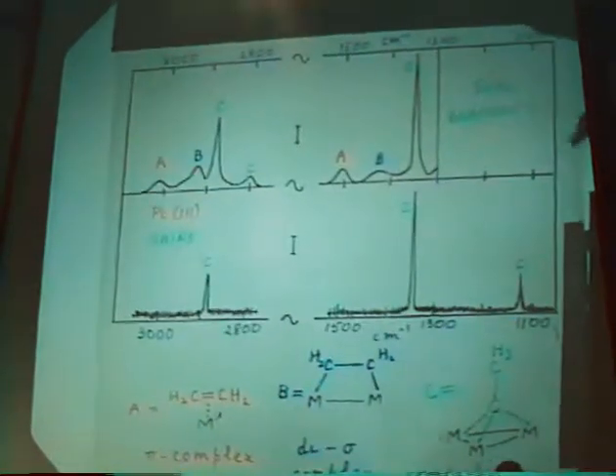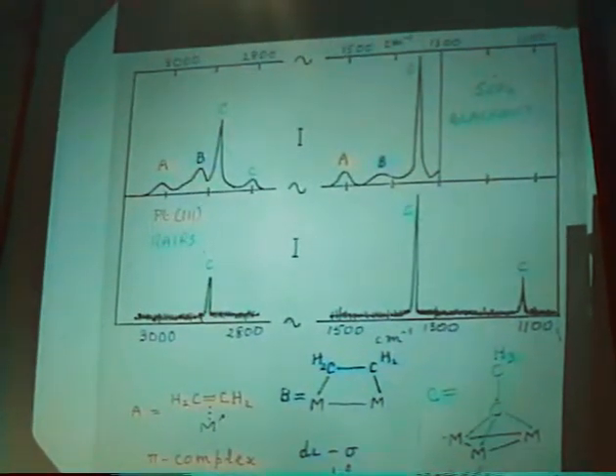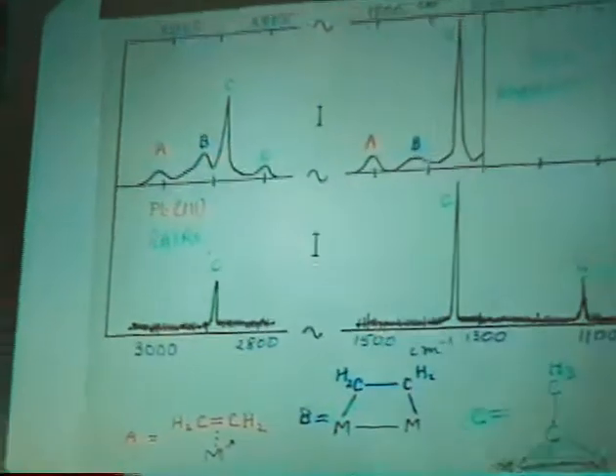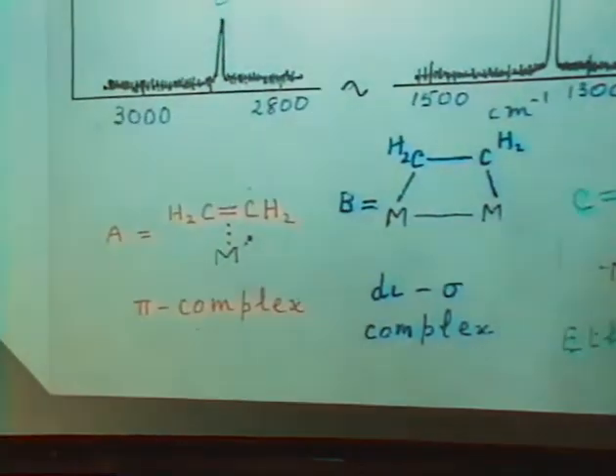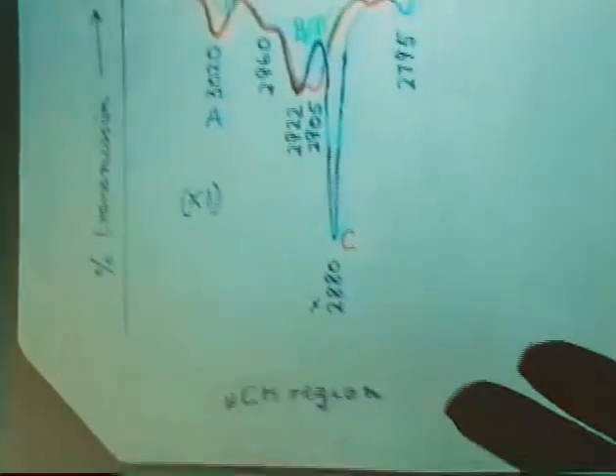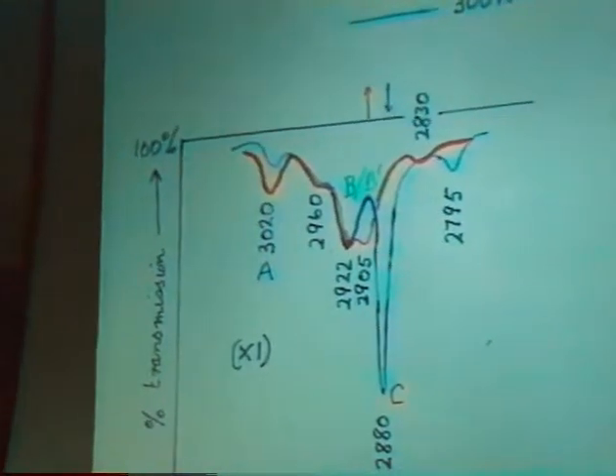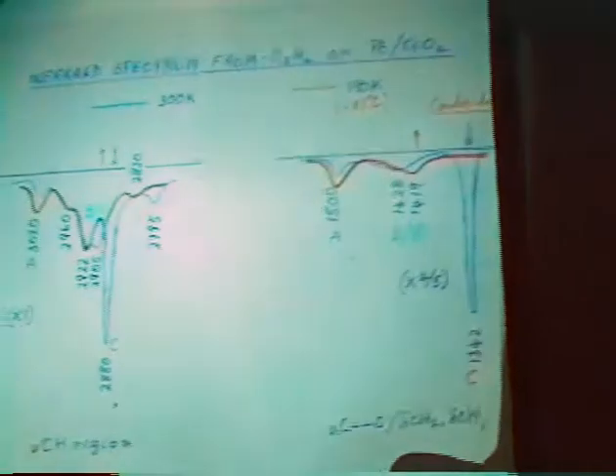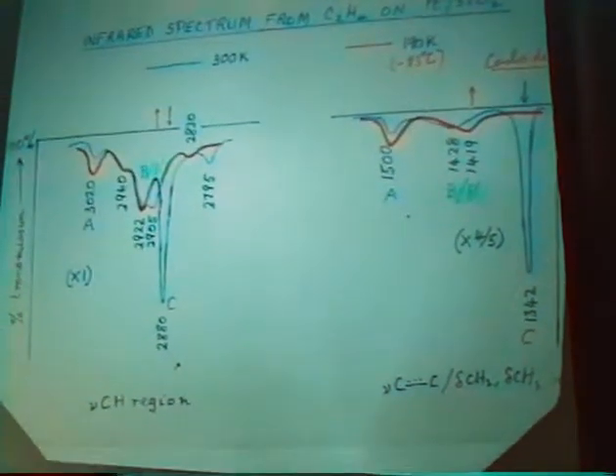And so now we can label all our principal absorption bands on the finely divided catalyst. C is our ethylidyne species. One other point I should have made was that of the two species close together at low temperature, only one of them turned into ethylidyne and presumably is di-sigma on the 111 surface. The other one remained behind. And so we assume this is also of the nature of di-sigma, but on a different, a non-111 surface.